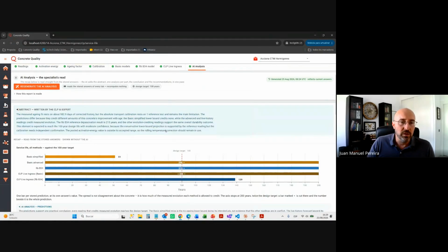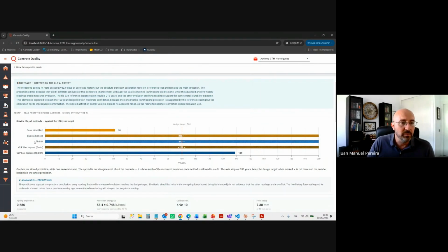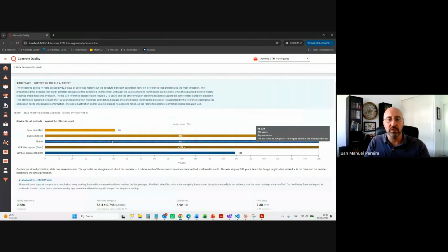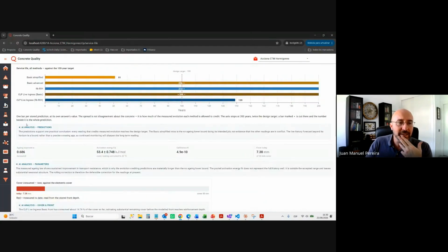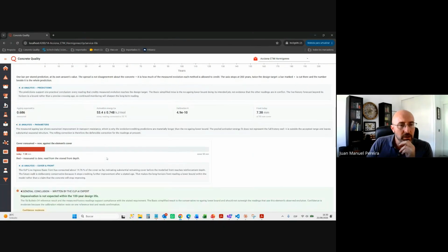So in summary, we have these different methods that give you different service life expectancies. The AI understands which one is better, which one is worse in which situation. It can compare all of them, and it can give you recommendations and predictions. For instance, here it is saying this is a good concrete because this coefficient is quite high. This activation energy is outside the normalized standard, so you need to keep working on it, keep measuring it.